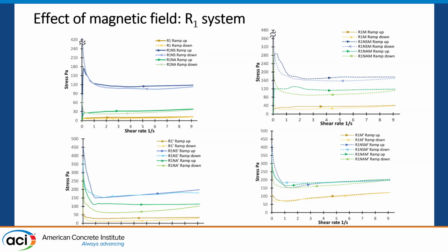Well, when we apply a magnetic field, rheological behavior is changing. For example, this is the pure Portland cement system, which I already reported on, and this is the system with a magnetic field. So the magnetic field is really helping us to enhance the response and provide additional stiffening. And specifically, both yield and stiffening stress are enhanced. If you look on the right-hand side, we have a system with magnetite powders. And again, magnetite was working well to enhance the response of a reference Portland cement system, for example, but maybe not as well as in enhancing the silica fume system.